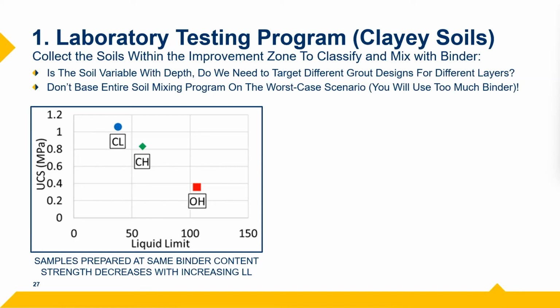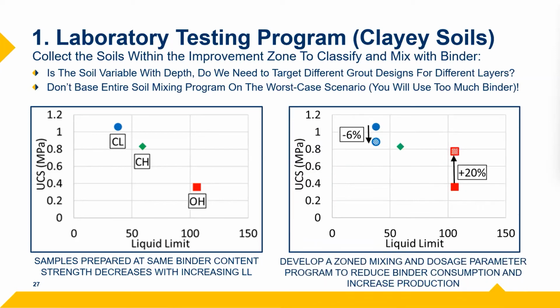And so if we think about it in terms of, oh, we need to have about 0.8 MPa strength, well, we're going to have to add a bunch more cement to that profile, right? Because the organic material didn't give us the strength we need. When in reality, what we need to do is make sure that we zone out our profile. And we have the equipment and tooling now, which I'll talk about a little bit later, that allows us to zone out these profiles so we can target the more problematic zones with a little bit more binder, a little bit more grout. And then in zones where we're getting better performance or performance closer to where we need it to be, we can actually reduce the binder in those zones. So we don't have to just use that single grout design for the entire program. We can very well zone out where we need to be with depth along the profile so that, again, all we're doing is making sure we put the right amount of cement in the ground.